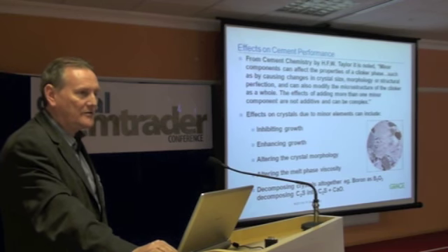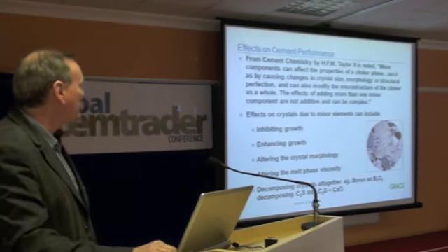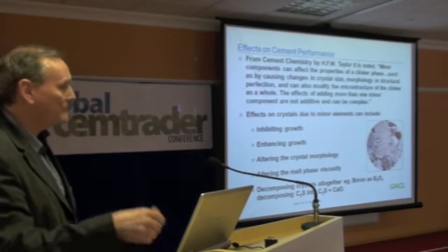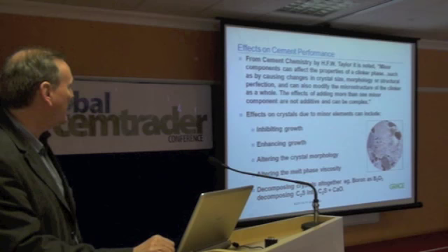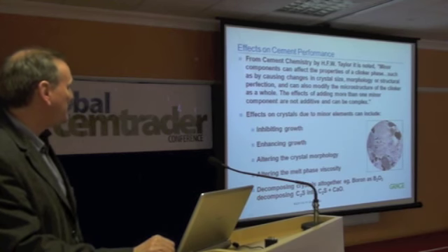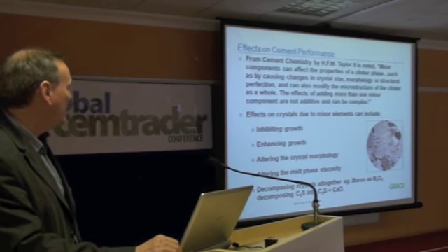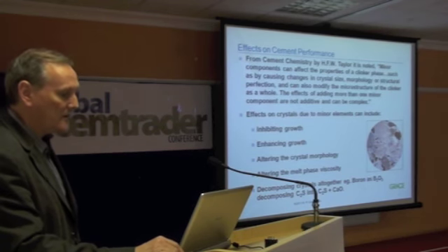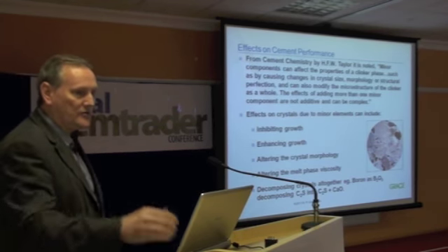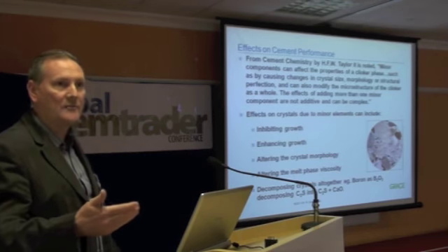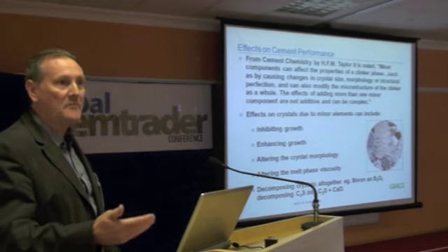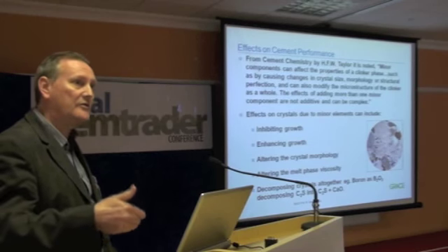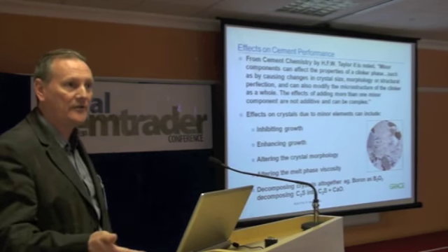You've got to really understand changes in the chemistry, the crystal size, the morphology, and the structural perfection and imperfections that are in the clinker making. And minor elements are known to inhibit growth or enhance growth of crystals. They can alter the morphology, they can change the melt viscosity, you can decompose crystals. Quite famously, the cement making processes react lime and silica. You actually make belite, C2S first, and then this reacts with excess lime to make C3S.